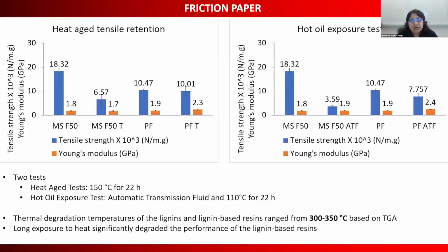So they proposed to us that we do two tests. One is the heat age tensile test, where the resin was exposed to 150 degrees C for 22 hours before testing it for mechanical strength. And the second test was the hot oil exposure test, where the kraft paper strips were dipped in automatic transmission fluid and then exposed to 110 degrees C for 22 hours. So this was to see whether our resins would perform well under more real world application conditions. However, this was not the case. This is before the heat age test. As you can see, the miscanthus resin shows much higher tensile strength than your PF resin.